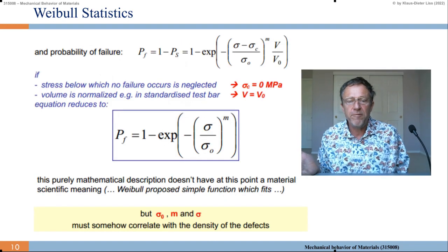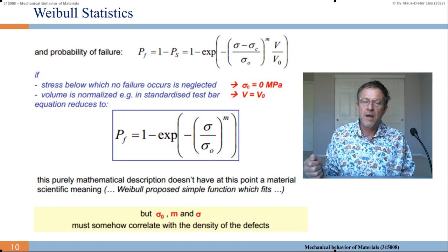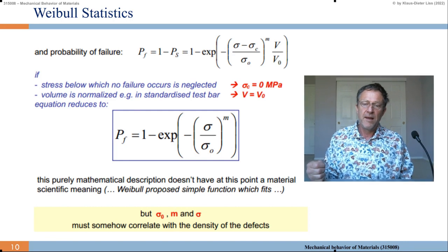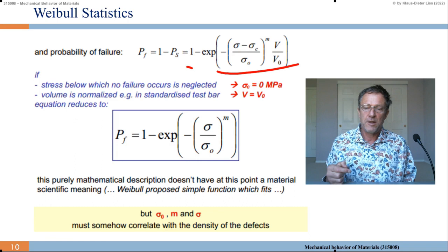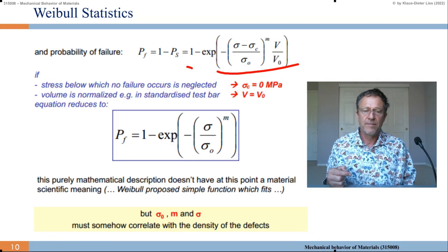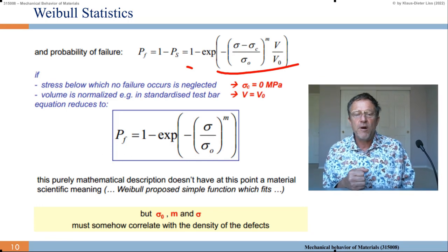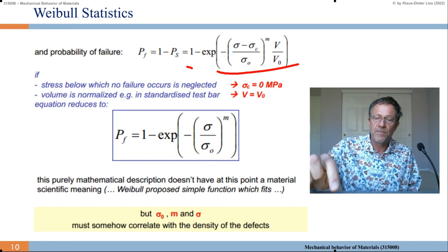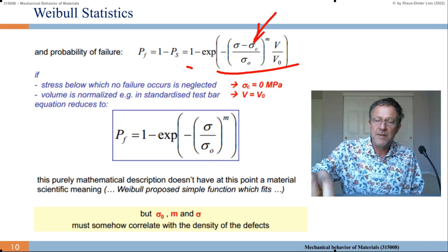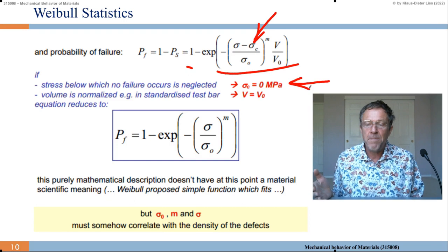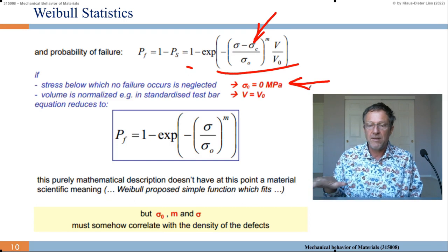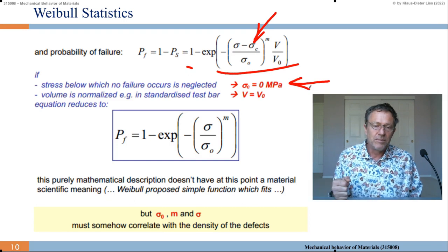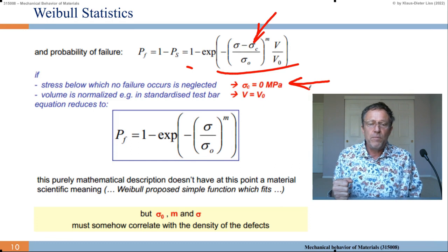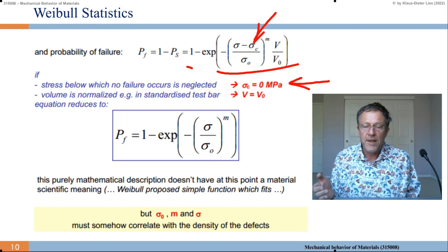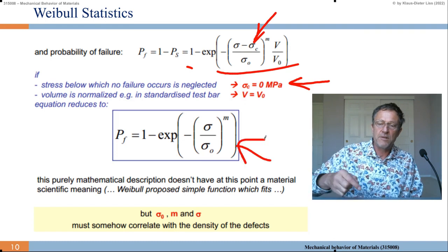And the probability of failure, of course, is 1 minus P survival. It's just 1 minus this exponential function. So if the stress below which no failure occurs is neglected, that's the sigma c, we say sigma c is 0 megapascal. That's an approximation. Let's say, okay, we just put it 0. And if the volume is normalized, let's say to a standardized test bar, then the equation reduces to this.